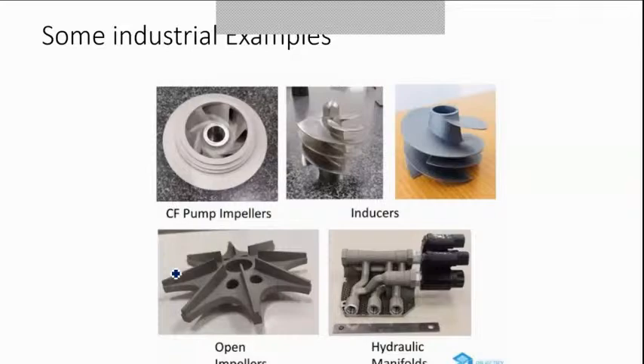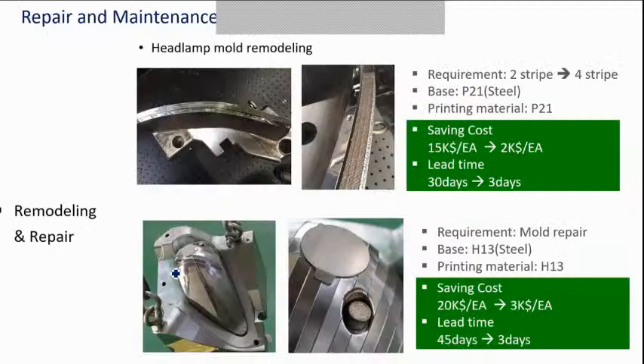The most interesting thing with the DED technology is that you can use it on an existing part, and on top of it, like welding, you can deposit new material. In this case, there is a scanner which is built in. It looks at irregular shapes which got created due to wear and tear or maybe due to breakage, and it immediately identifies those areas, and you are able to deposit the same material which you had before.